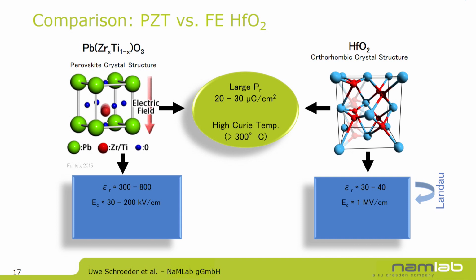the field you need for switching would also be a factor of 10 different. And from the scaling point of view, typically PZT was used in capacitor structures down to 70 nanometer, and then an issue started with interfacial layers and depolarization fields. For the hafnium oxide, ferroelectric properties were shown down to 5 nanometer and below, even in the 3 to 2 nanometer range for the material.